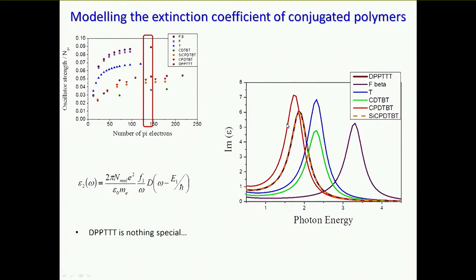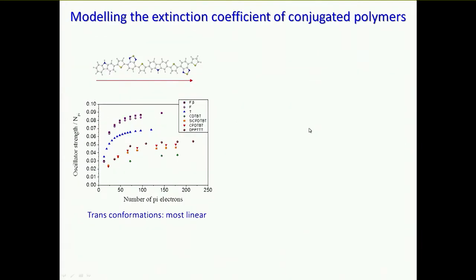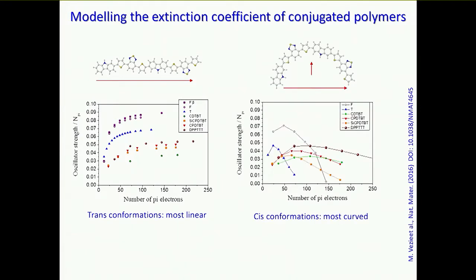So we were a bit puzzled, and we then needed to go back and think again about the calculations that we'd done. And when we did these calculations, we prepared our chains in a way where we alternate. Typically, in our conjugated polymer, we will have a torsional potential that minimizes the energy of the structure when two neighboring monomers are either aligned in a trans or a cis configuration, and we had tended to align them in a linear fashion. But if that torsional potential is more or less balanced so that your polymer is just as happy to be like this or like this, they might also have aligned in a different way.